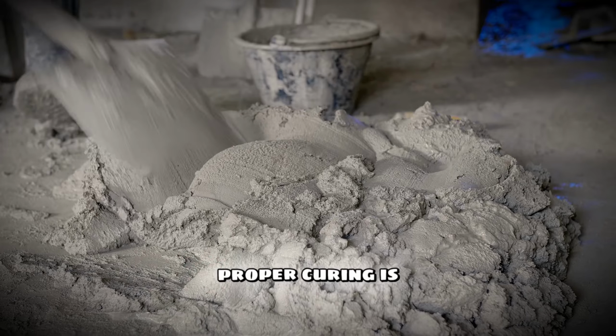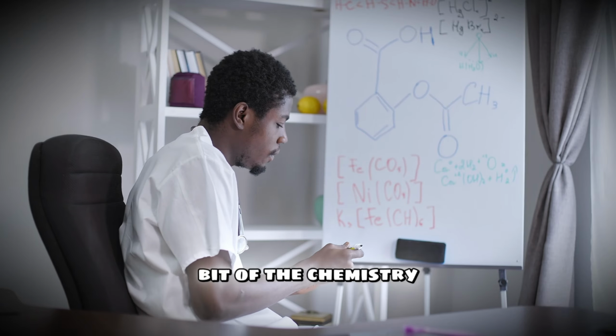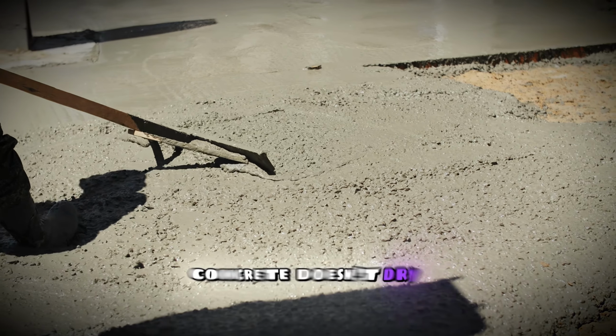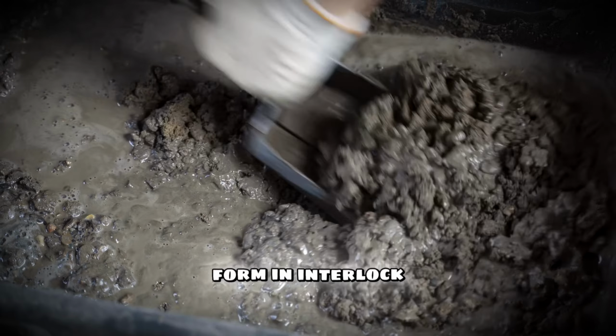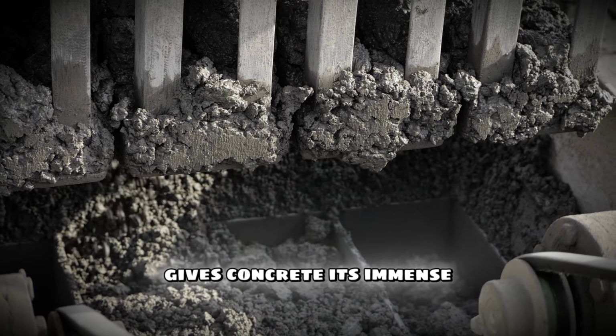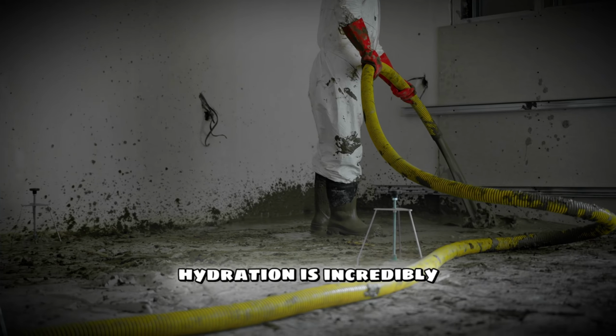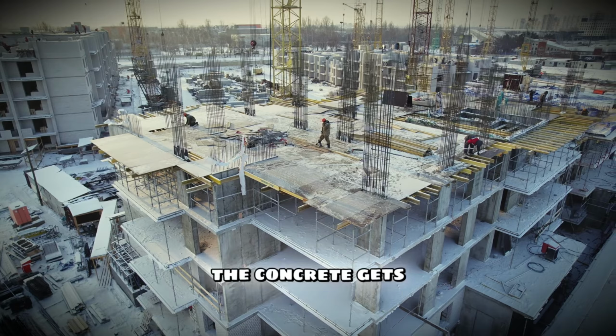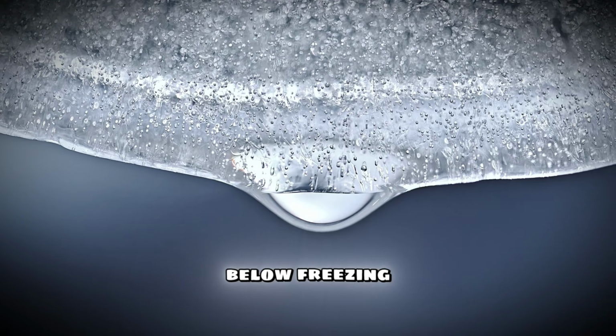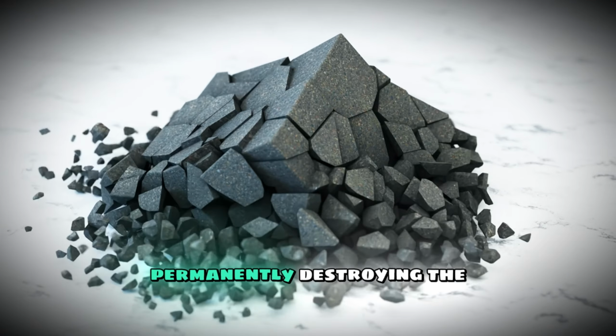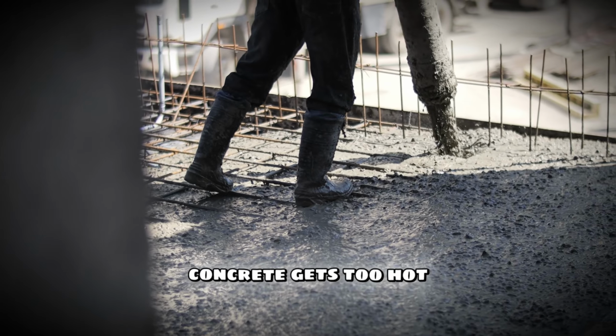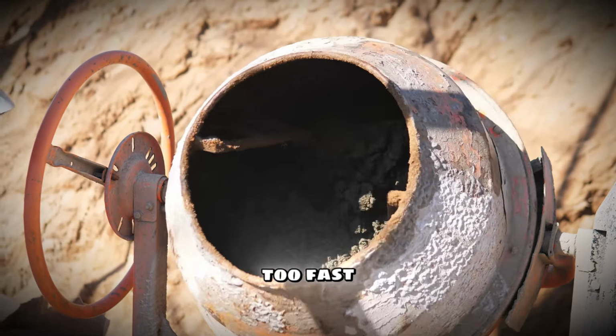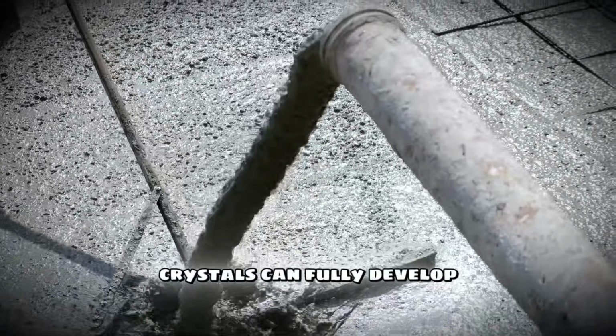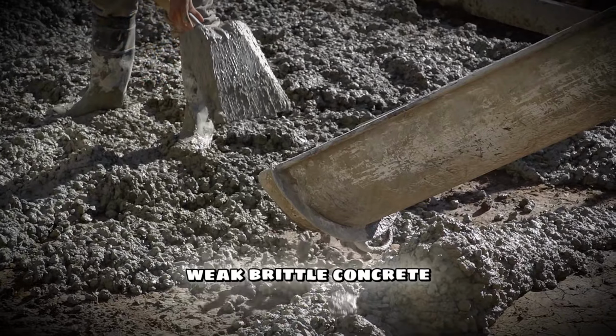To understand why proper curing is so critical, you have to understand a little bit of the chemistry. Concrete doesn't dry. It cures through a chemical reaction called hydration. When cement meets water, crystals begin to form and interlock. This interlocking matrix is what gives concrete its immense compressive strength. Hydration is incredibly sensitive to temperature and moisture. If the concrete gets too cold, the hydration process slows down dramatically. If it drops below freezing, the water inside expands, permanently destroying the internal structure. On the flip side, if the concrete gets too hot, the reaction happens too fast, and the moisture evaporates before the interlocking crystals can fully develop, leaving you with weak, brittle concrete.